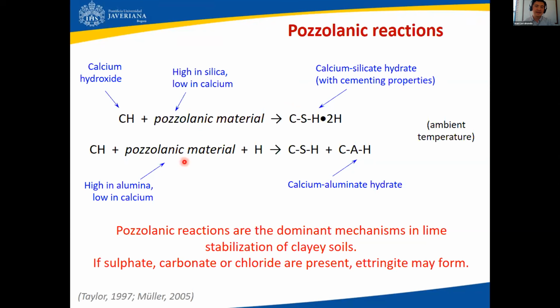Now, if the pozzolanic material is high in alumina as well, you also typically get calcium aluminate hydrates, both of them at ambient temperatures. What is interesting is that the study of pozzolanic reactions is a very widely known and well-studied field in lime stabilization or even cement stabilization of swelling soils. However, these principles have not been very well or deeply studied for the field of contaminant barriers. So that's where we are looking at right now in this present study. I just want to mention that if certain phases like sulfates, carbonates, or chlorides are present, these same reactions may produce ettringite. And this mineral, ettringite, is a complicated mineral for engineering applications because it also has swelling properties as well.